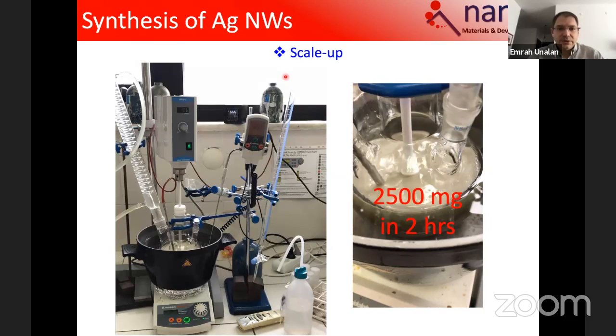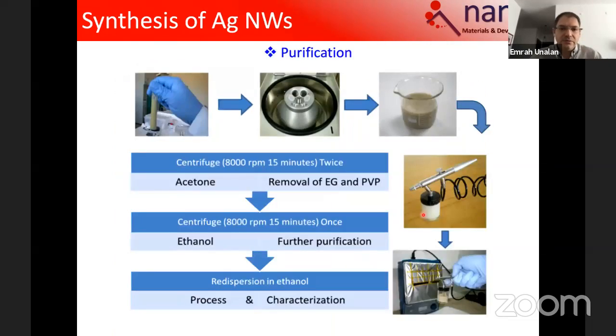And when we started with Dr. Coşkun in 2009, I believe we were getting 40 milligrams of nanowires. But with the forthcoming processes, projects, necessities, we now enlarged our growth, so we can get more than 2 grams of silver nanowires easily in 2 hours. So scale up was possible. If there is demand, certainly we can also increase the growth further on, or at least multiply the number of synthesis setups very easily.